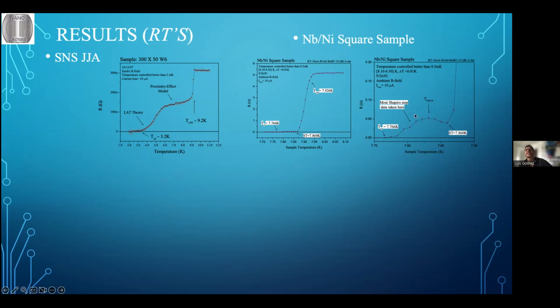At this point, we had the most error. There are the most fluctuations. This is the size of this red error bar over here. But on the other parts, the error bars were negligible. Whatever we measured as the resistive point, we calculated it basically by sending a fixed current and then measuring the voltage in both directions. That's how we determine the resistance, the ratio between the voltage and the fixed current. So there's more error in this region than you have below, I mean, at colder temperature, or even before that.